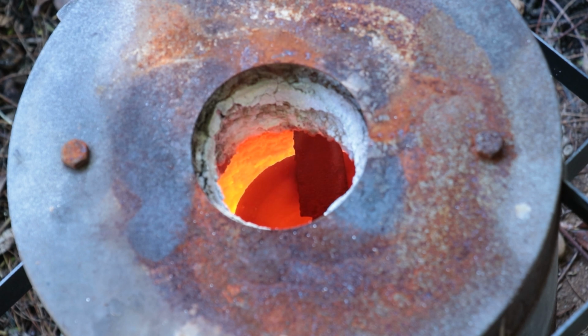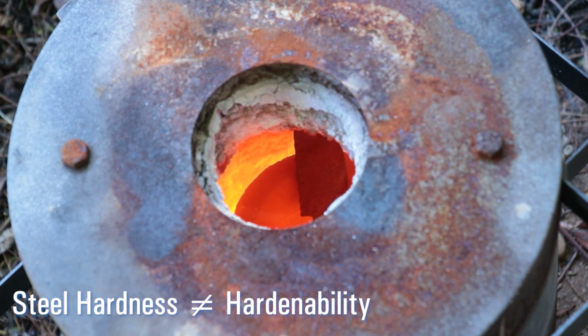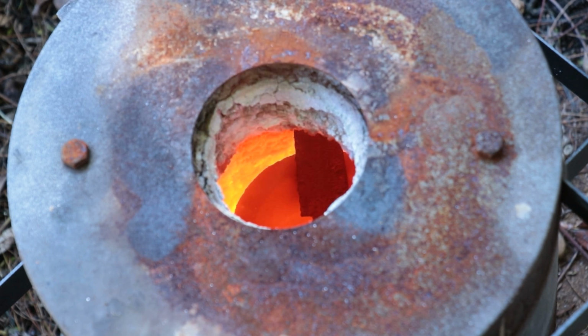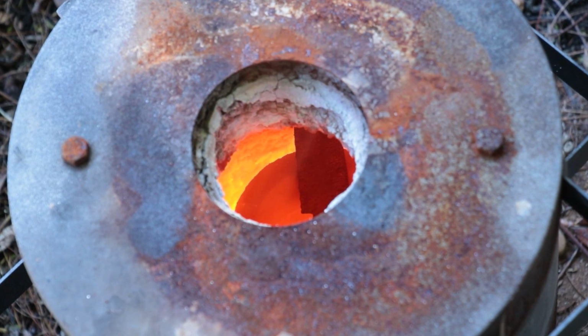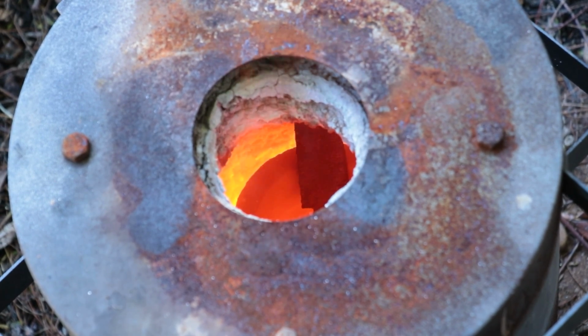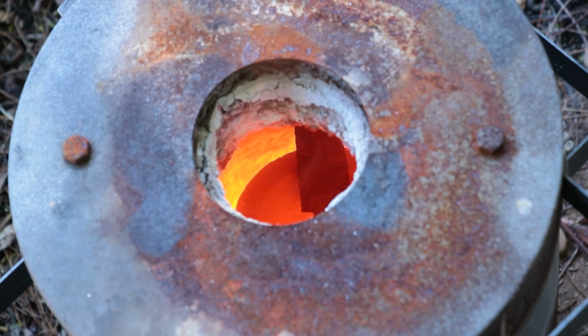Like I said before, we're effectively resetting the internal microstructure of the steel, so how we go about cooling it will determine the microstructure and the hardness. Now, even though we should be able to get a high degree of hardness from this steel, plain carbon steel has a lousy hardenability, which among many things means we need to cool it down very quickly to achieve that maximum hardness. For plain carbon steel, for example, we have about 1 second to get it from red hot down to about 150 degrees Celsius to get it hard.